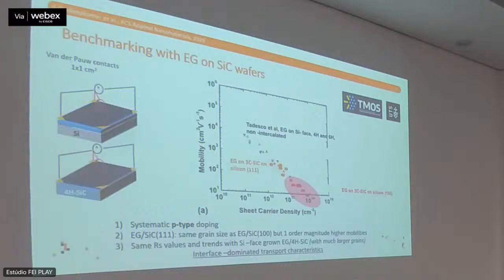So they don't change independently, of course. It follows a power relation. So in a log representation, you should get more or less a straight line. This has been shown already for graphene on silicon carbide wafers. These are the triangles, the silicon carbide points that we took as a benchmark. You can see that all of the points sit on more or less a straight line, and all the points, of course, have the equivalent sheet resistance.